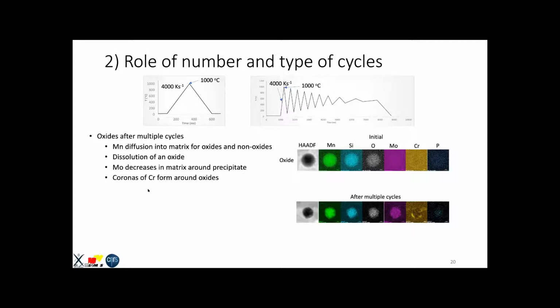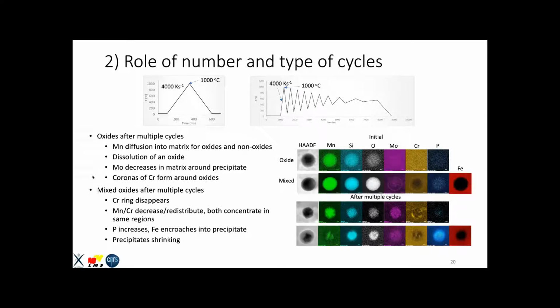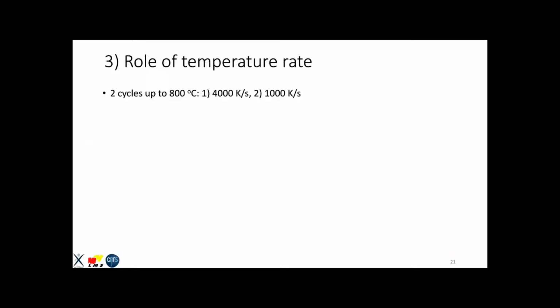So that was interesting. And then we started seeing coronas of chromium formed around oxides. Now, these were similar to the coronas that we saw that were already present in the as-built material. So this was something that we found that, yes, it's a bit representative. Mixed oxides, we started seeing that these coronas were disappearing. Manganese and chromium were beginning to decrease and redistribute, and both were concentrating in the same region. Phosphorus increases in general, and iron is encroaching onto the precipitate. So we thought that, okay, here the precipitate is shrinking in size. It's going to probably disappear at some point if we had continued.